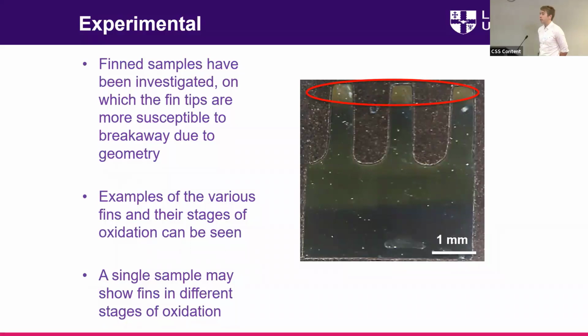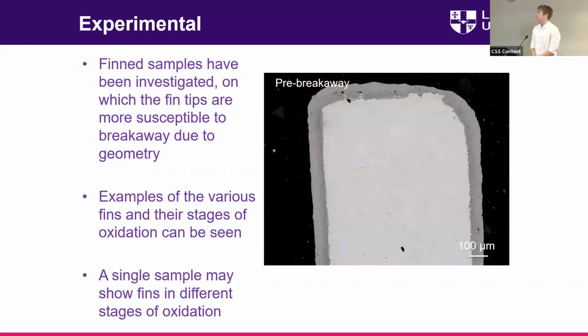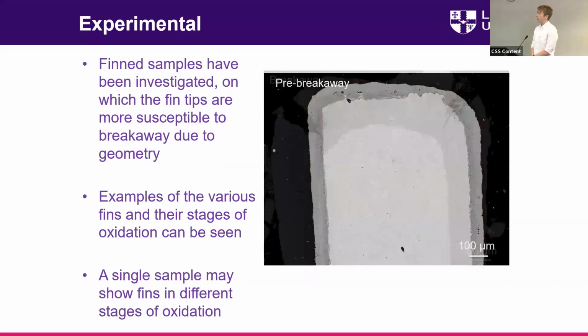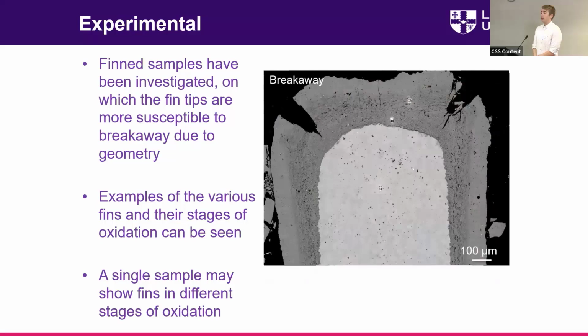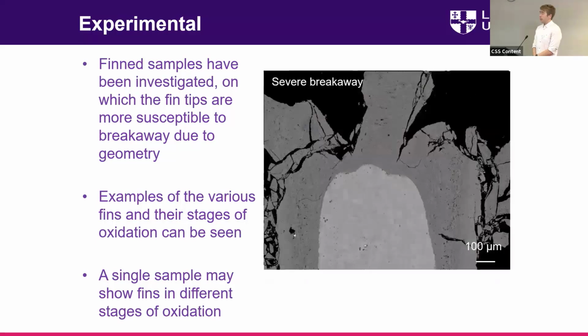I'm just going to show some examples of what we'd class as a pre-breakaway fin and a breakaway fin. This is considered a pre-breakaway sample, and you can see a relatively uniform oxide layer around the whole of the fin. This would be considered breakaway, where the oxide scale is a lot thicker and there are also cracks coming in from the corners. And then a severe breakaway sample here, which would be one which has had continued exposure after breakaway is initiated, and the oxide is just rapidly growing and peeling away, so you get spallation of material, which obviously we don't really want.